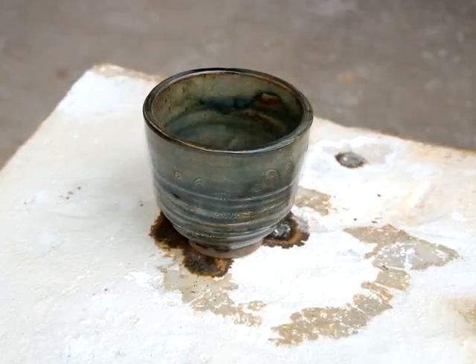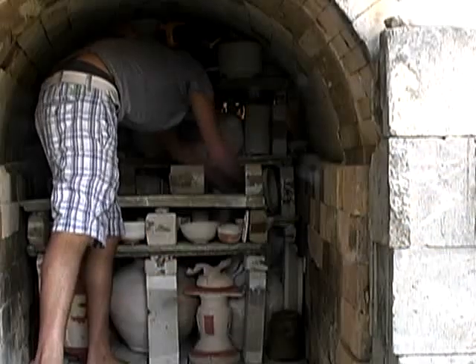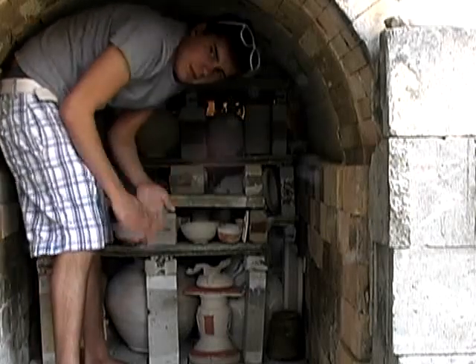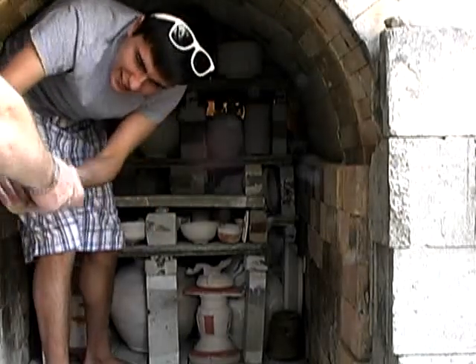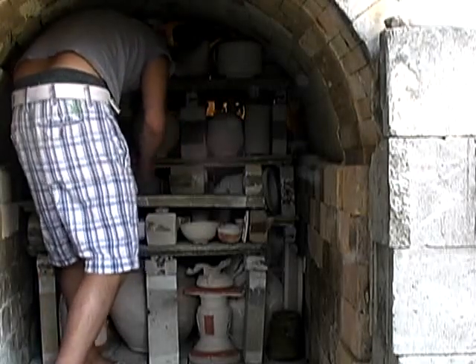It is important to remove glaze that is too close to the bottom of the piece because it flows downward when heated and may stick the object to the shelf of the kiln. Once glazed, the piece goes back in the kiln for a second time for a glaze firing. The temperature must be significantly hotter than for bisque firing.